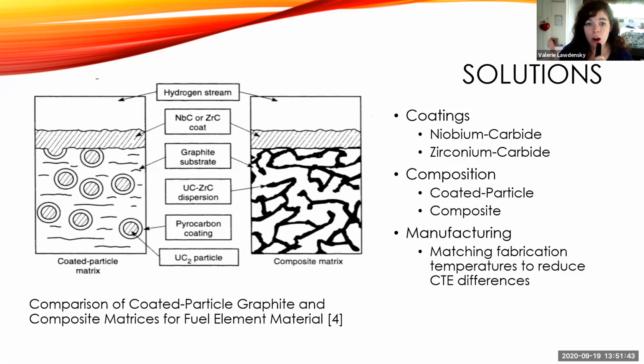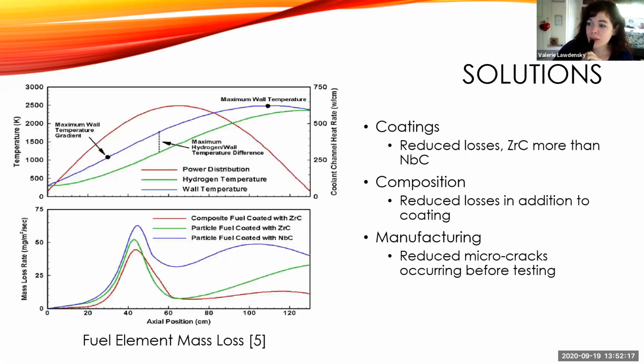They tried zirconium carbide and niobium carbide. Niobium was first, and it had this benefit of being substantially higher than that maximum operating temperature, which these can reach 3000 Kelvin. So generally, when you're trying to decide what to do with any other material, it can't melt below 3000 Kelvin. So niobium was great. It was plenty above that. However, it didn't really bond to the fuel elements, and it just didn't do very well compared to their next attempt, zirconium carbide, which bonded exceptionally well and actually helped reduce it. We can see from here, where on the bottom graph, the niobium carbide is the blue, where you still had some.